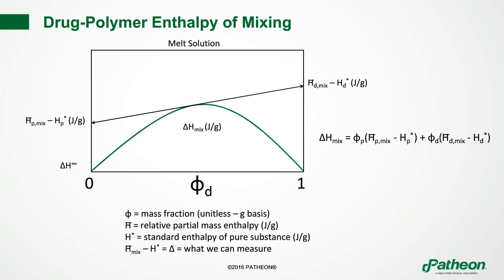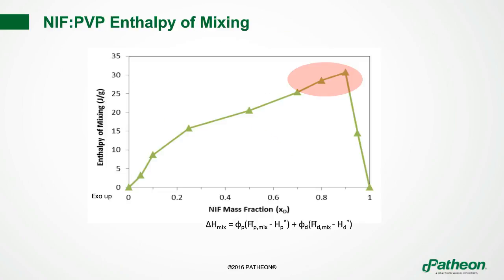Now when we do that, what we actually see is demonstrated in this slide here. This is some real experimental data that we've measured using nifedipine and PVP, looking at the enthalpy of mixing. We used differential scanning calorimetry and then calculated the ideal heat of mixing, as if both components didn't actually mix, and then we look at the non-ideal behavior. So what's the difference between what we measure and what we expect?